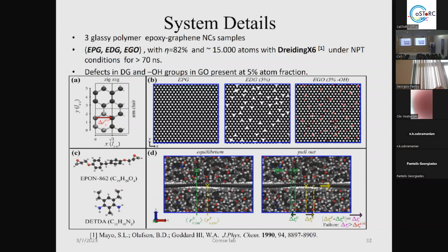Now, the phenomenon that we wanted to explore was this: as it is here, in the system we tried to pull out the graphene, and you can see that with a yellow arrow. Of course, to keep the epoxy from moving, we applied another force on the epoxy resin, with a green arrow. So we tried to pull it out in order for the interfacial failure to happen.